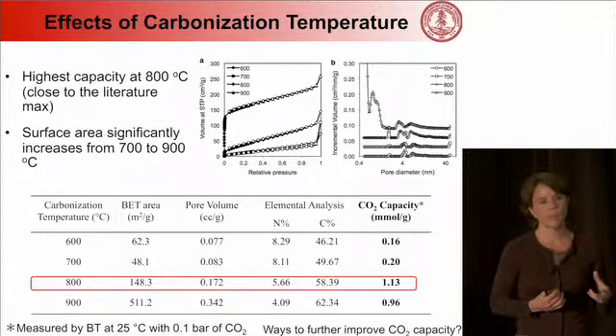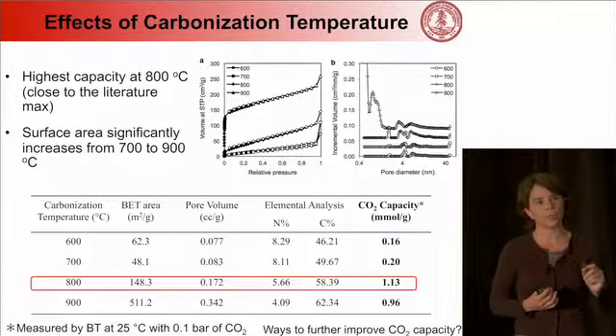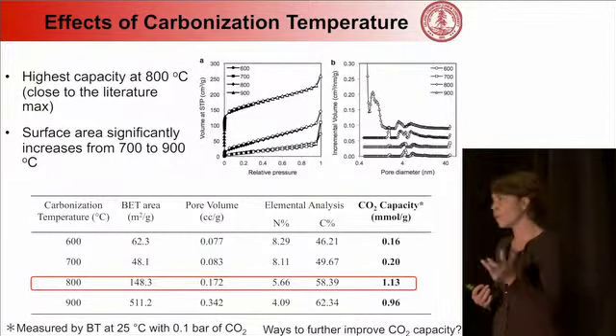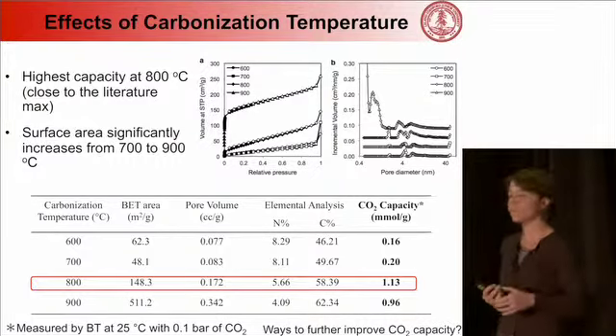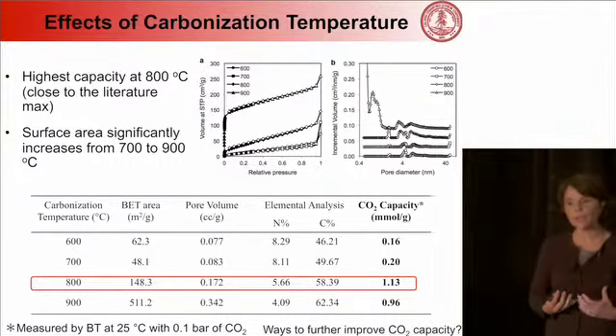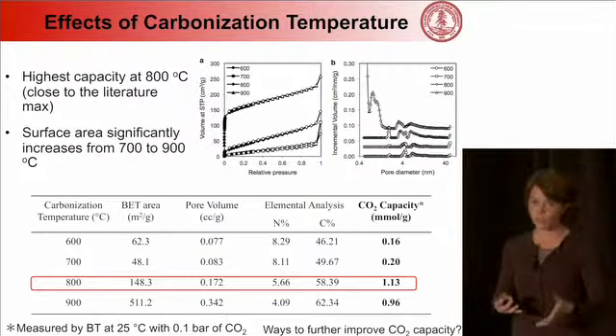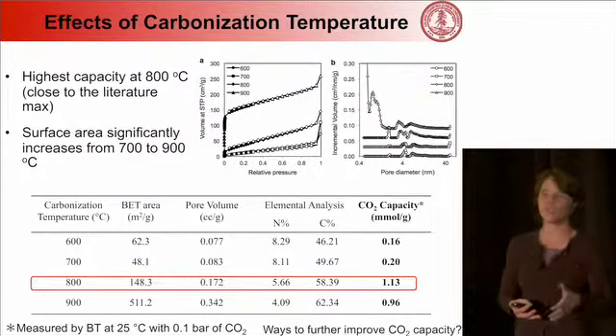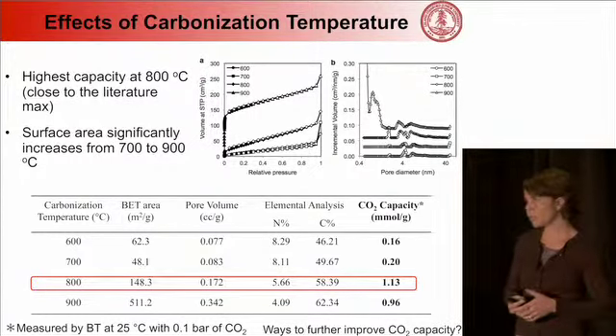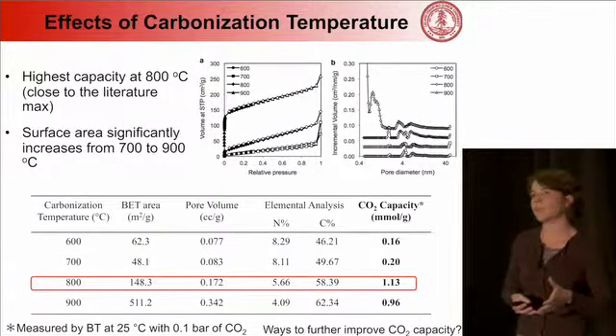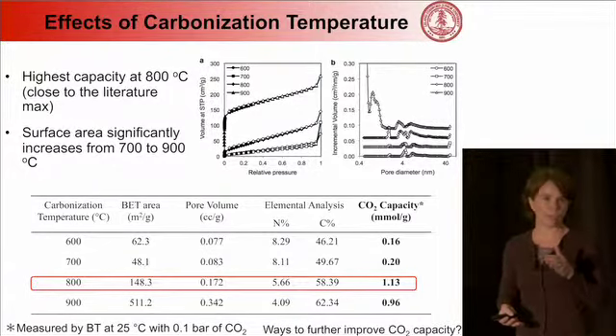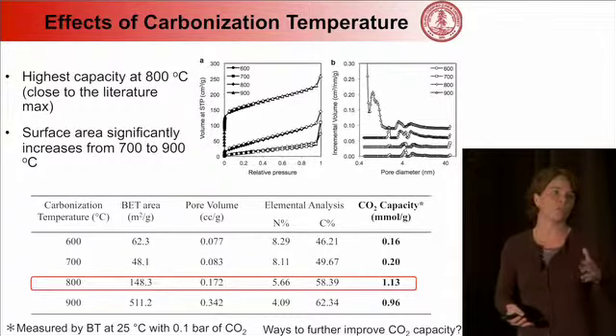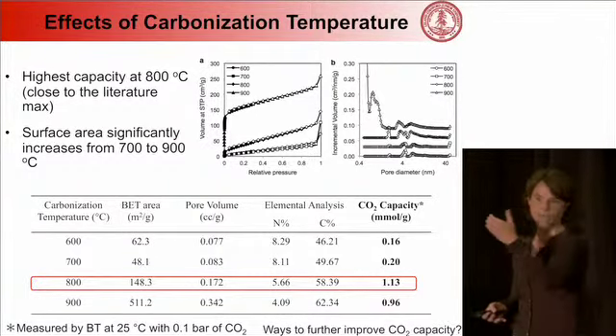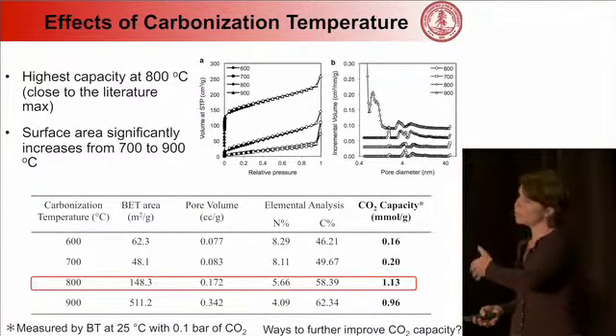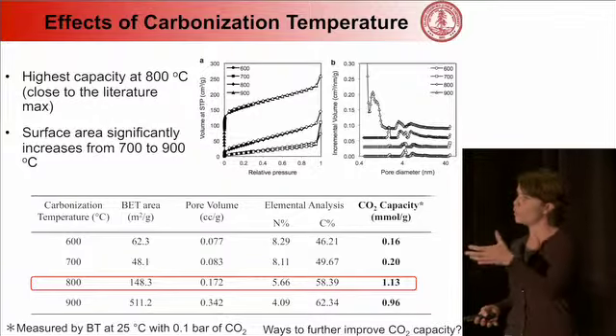So again, depending on what the pore size is and what the partial pressure of CO2 is in the atmosphere or in the flue gas that's in equilibrium with our material, will dictate whether or not we can actually take advantage of a thermodynamic driving force in addition to a chemical driving force. So for instance, when I talk about kinetics and I talked about zinc, that had to do with the actual kinetics of the chemical binding of CO2 to the zinc. And if we have a nitrogen functional group, there might be the chemical kinetics of CO2 binding to the nitrogen.